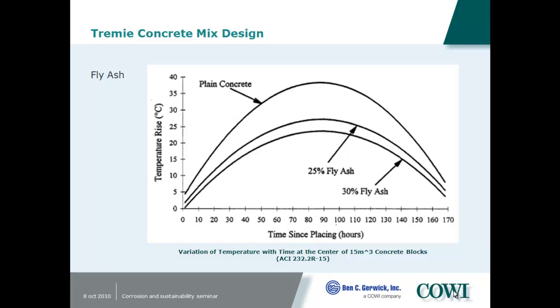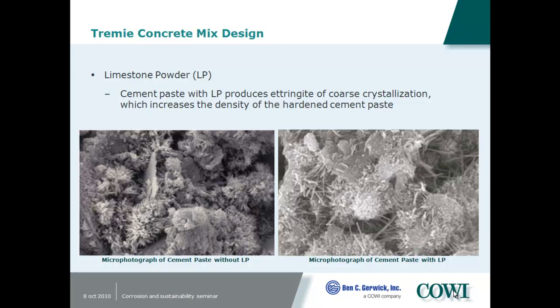Tremie concrete, even with only 14% cement, we were still getting very good strength gain with our Tremie concrete mix designs. Here's limestone powder. It's just mined and ground into a powder, and it can promote the formation of ettringite, which is not a problem so long as the concrete is fresh. If it happens after the concrete is hardened, it can be a major problem as it expands, but actually it's kind of good to get the ettringite done while it's fresh, because then there'll be less propensity for it to react later on.